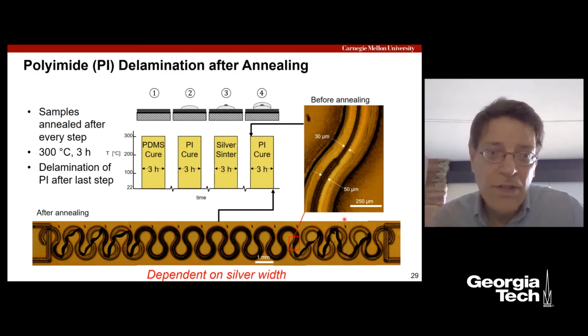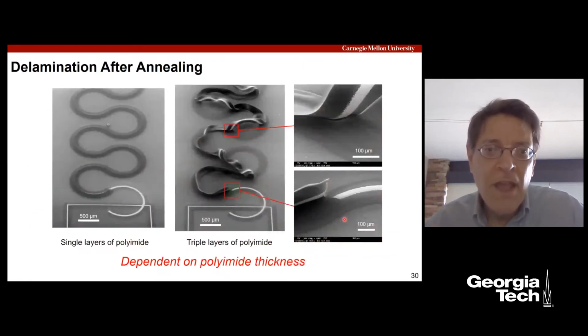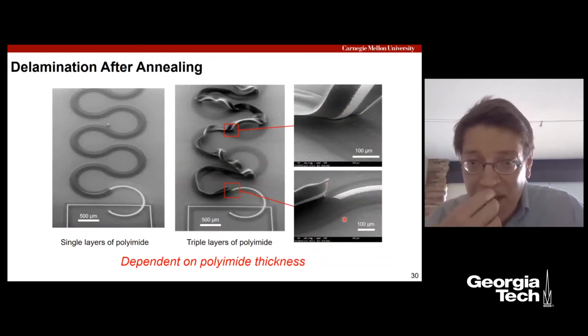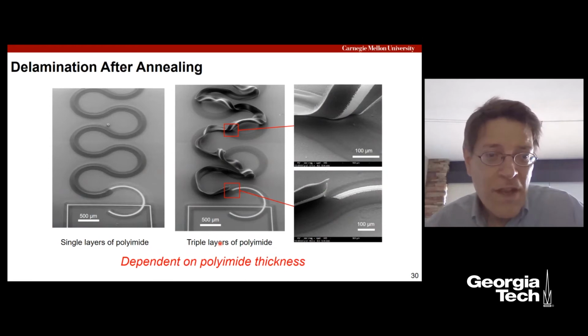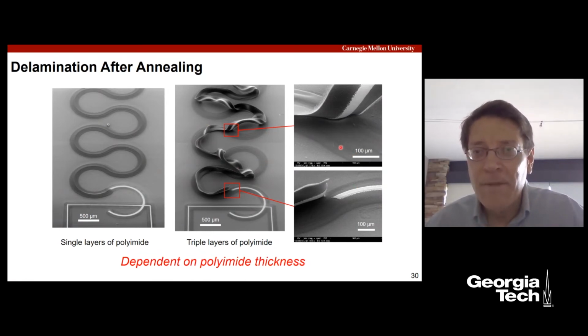What's going on there? So it's clearly dependent on the silver width. It's also dependent on the polyimide thickness. We found that when we would aerosol jet single layers of polyimide, we got beautiful wiring. This is in SEM, and here this is a triple layer of polyimide, so it's on the order of 6 microns thick, and we're seeing the clear delamination, and it's delamination of the polyimide to polyimide. It's not peeling from the PDMS. The bottom polyimide is staying on the PDMS. It's literally peeling apart the first and second layer.